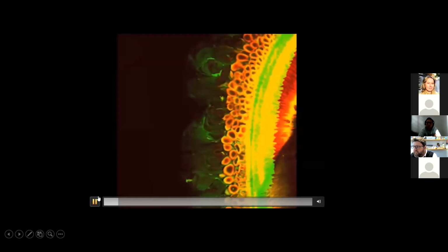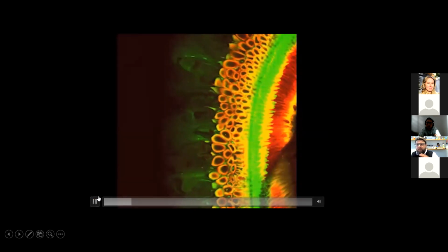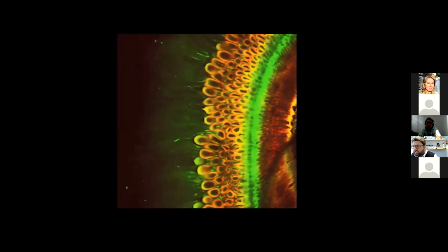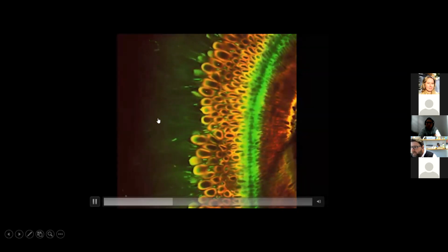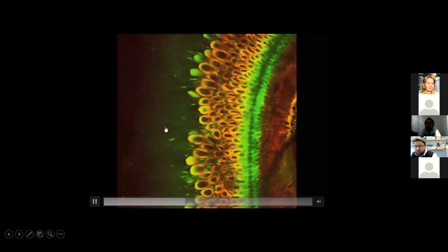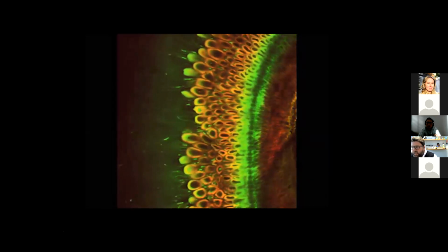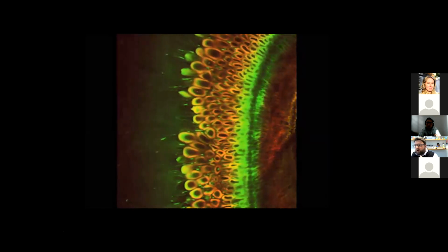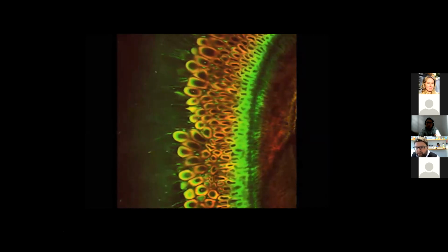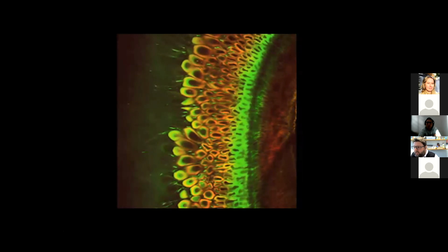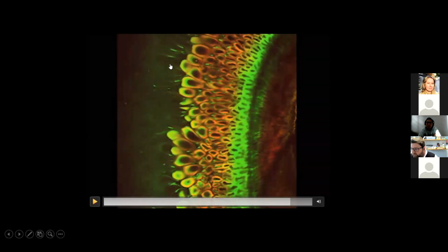So I press the play video, and you can see the expansion of the mucilage due to hydration. So obviously this is the sped up video. And you can see that when this expansion is happening, it is not a homogeneous material. And different colors correspond to different stains. So in this case, it is the calcofluor white and direct red 23. And so you can see that there is a formation of three layers.